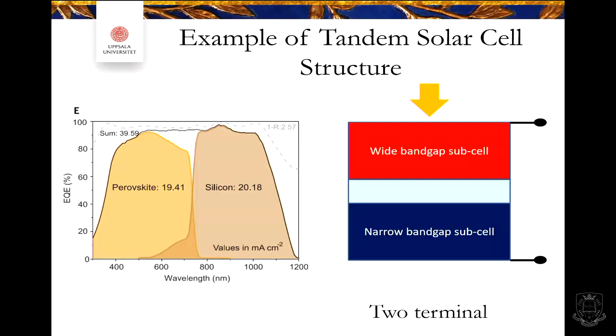And here you see a two-terminal version. So then the first layer here is the perovskite layer. It has a wider band gap, so it's in this wavelength range from maybe 300 over to around 800, and then below is the silicon solar cell device. And this is called two-terminal when you have one contact there and one contact there, and you measure over the whole solar cell. There is also what can be called a four-terminal solar cell. Then you just place two solar cells above each other. So then you also have a contact here and a contact here. That is the four-terminal solar cell device, which is also a possibility to work on and develop.